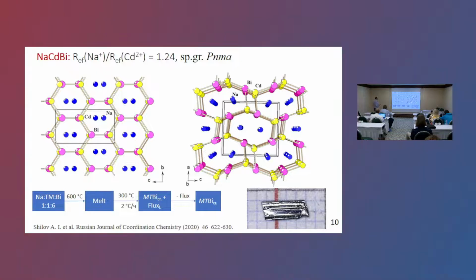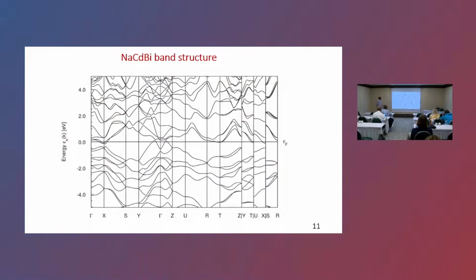As a result, we prepared some bismuth compounds. In this picture, we can see sodium cadmium bismuth. This crystallizes in an orthorhombic space group. In this structure we can see graphite-like layers, but there is some connection between these layers, and sodium sits in the holes in this structure. Band structure calculation shows us some interesting details of the physical properties of this compound under investigation.